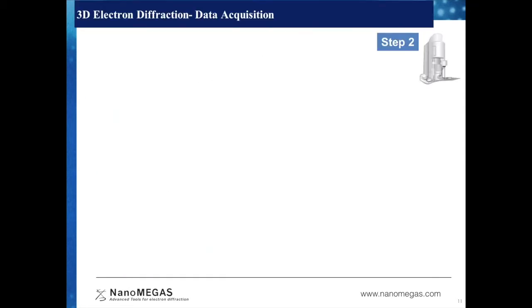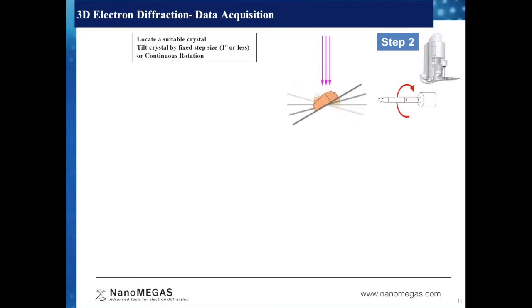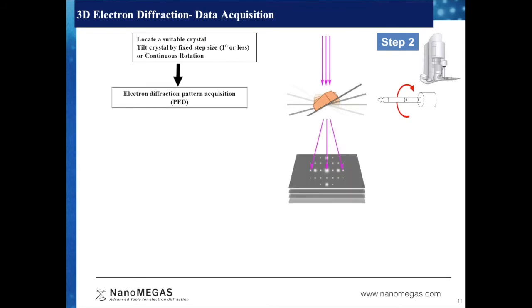Next, step 2, to acquire the three-dimensional electron diffraction data. So to acquire the 3D electron diffraction data in TEM, first one has to find the crystals in the TEM grid which are beam transparent and separated from other nearby crystals. Only then can one start collecting the data, either by tilting the crystal stepwise or by doing a continuous rotation of the crystal. Electron diffraction data are usually acquired with beam precession to get better quality data, which I've already mentioned a few slides before, and that's what we always recommend.